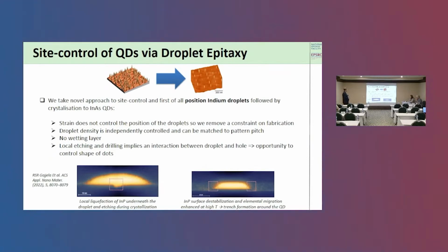So we take this novel approach, which is that we want to use the droplet epitaxy approach for site control. So instead of trying to site control the quantum dots directly, what we have looked at is positioning, first of all, the indium droplets, and then the conversion of those indium droplets into dots through the droplet method, but in etched pits. So there are some advantages to this.